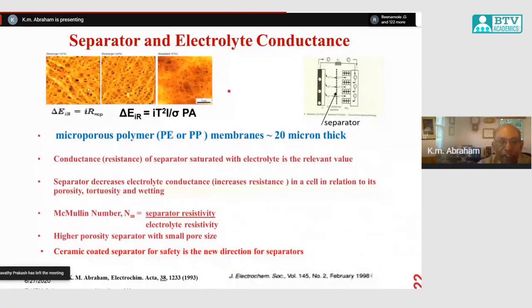You want to look for a separator with high porosity and small pore size for lithium-ion batteries, because the higher the porosity, the better the conductivity, because the ions have to move through the separator. The separator in the battery is soaked with the electrolyte. It separates the two electrodes, but there are very tiny micron-size holes in there through which the ions can pass.